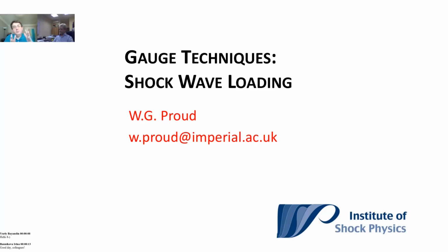So with failure waves, it's almost like elastic decay in terms of the phenomena. It's like elastic decay, but on a bigger scale. You're dealing with things that take microseconds now, not sub-microseconds like a lot of the precursor decay phenomena. Things are occurring over long microseconds, and you see that more. You see that step. You can use a similar type of explanation to look at elastic precursor decay.